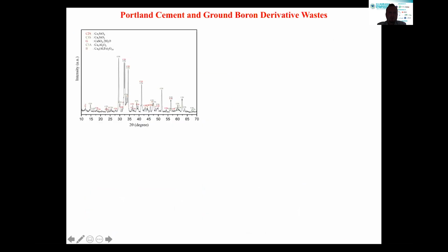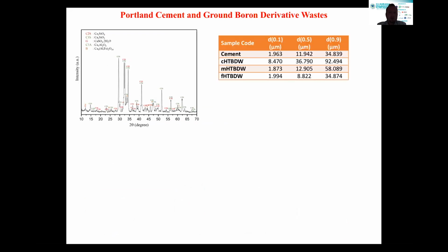As you know, the Portland cement includes calcium silicates, gypsum, calcium aluminate, and boron mineral phases. So what's the particle size distribution of the cement and wastes? You can see here the coarse heat-treated powder has a much broader particle size distribution. The medium powder has an equal median particle size compared to cement, but the particle size range is slightly broadened, and the fine powder has exactly the same particle size range compared to cement.